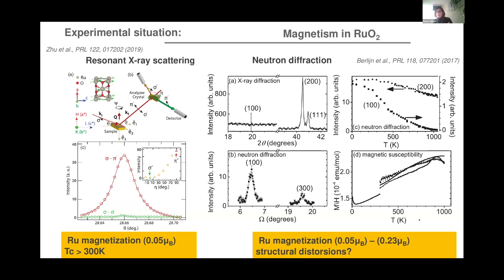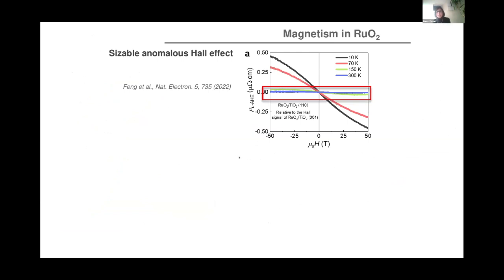However, there is a discussion in this work whether they have some structural distortions, so whether they can distinguish this ordering from structural distortions, and this is what I will comment on in a moment. So indeed, as we can see, there seems to be a controversy between different types of experiments. Maybe the last experiment I would like to mention is anomalous Hall effect by this group, where they seem to find also in ruthenium dioxide a sizable anomalous Hall effect. And if you deduce from these measurements the magnetic moment, it is in fact much larger than the magnetic moment that was deduced for the previous two experiments that I was showing.